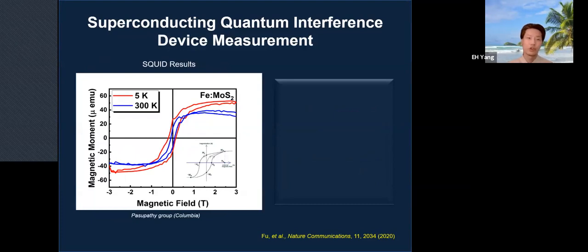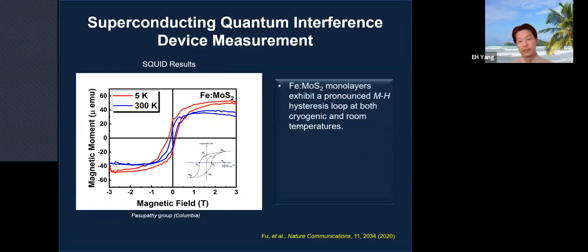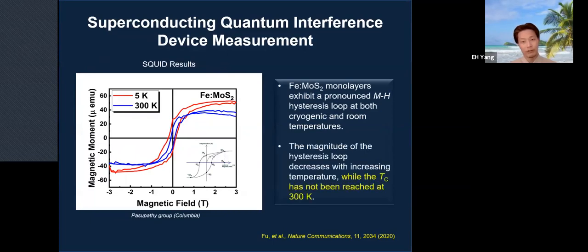So we used the superconducting quantum interference device measurement, and the measurement was done at Columbia University. And this graph shows that the monolayer exhibits a pronounced hysteresis loop at both 5K and 300K. Of course, the magnitude of the hysteresis loop decreases with increasing temperature, as shown in this figure. However, the Curie temperature has not been reached at 300K, which means that the material remains magnetized at 300K again. So this is double, triple confirmation of the room temperature magnetic property, all right?